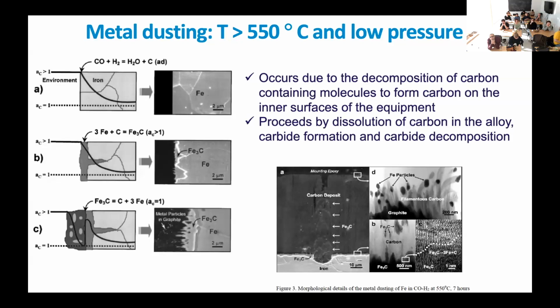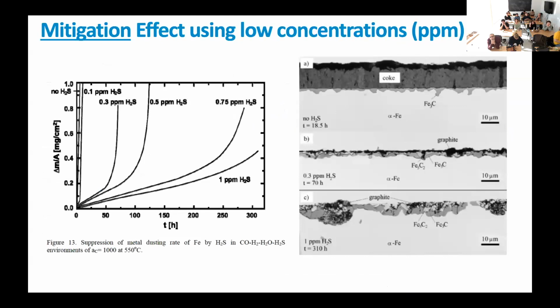Now, if we look at the main question, this was a very well-known problem, but the main question that industry had is this: in order to mitigate it, they introduce very small concentrations of H2S, ppm concentration, which is parts per million. And you see that in this case the corrosion rate decreases as they increase the amount of H2S they introduce. It's common practice, okay? They need to balance it to avoid other phenomena. But they wanted to know what is governing it from the atomistic point of view and how it is happening. And how could we find the optimal H2S concentration depending on the gas mixture?